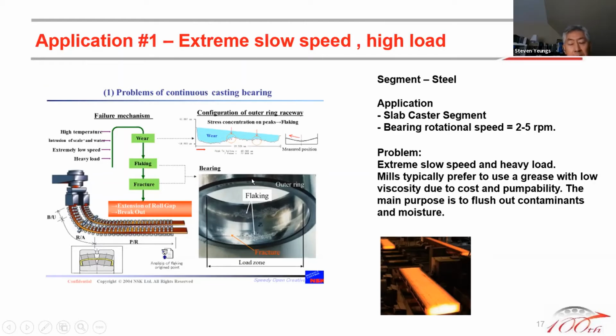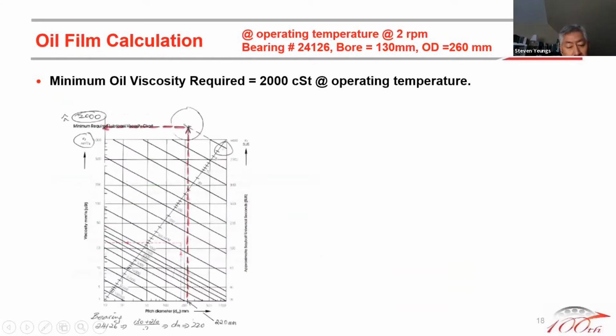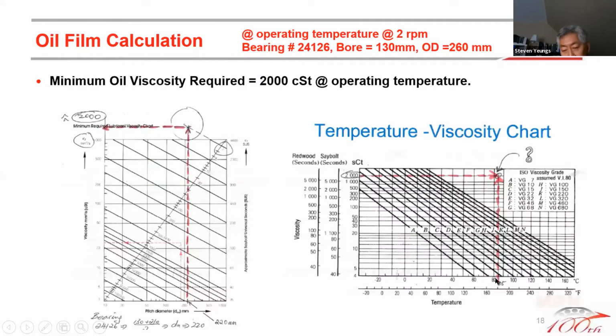But with such a low speed, if you try to look at the oil film, it's similar to what I was doing earlier, looking at the bearing size, and then looking at the speed of that bearing. And then if you go across at operating temperatures, you're looking for a lubricant grease that is close to 2000 centistokes. And when you try to factor in the operating temperature at 85, you are looking for something that may not be commercially available. You're not going to look for something that is super heavy, because it becomes not practical to be used in this application. So this is what I said about oil film.